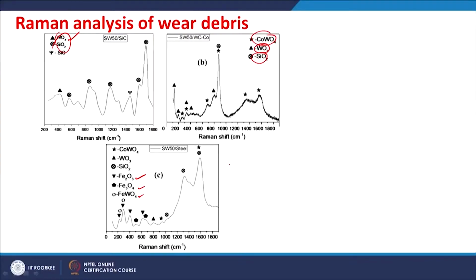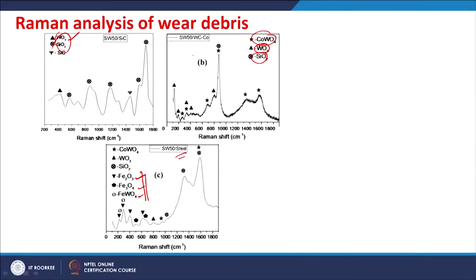So, it actually indicates there is a chemistry difference in the debris formed when these composites were subjected to sliding against different counter bodies. The friction is more when these were worn against steel because of the presence of the harder oxides of iron or iron tungsten oxide, and these iron tungsten oxides are not present in the other conditions. So, you do not have such an increase in the friction.